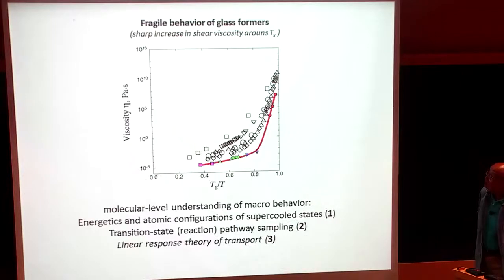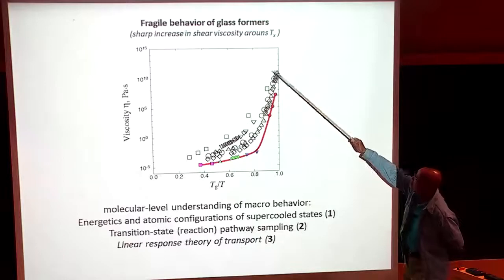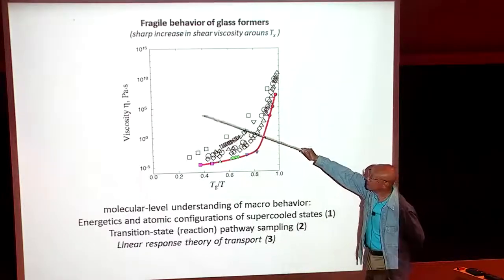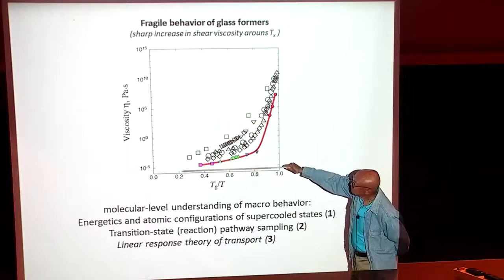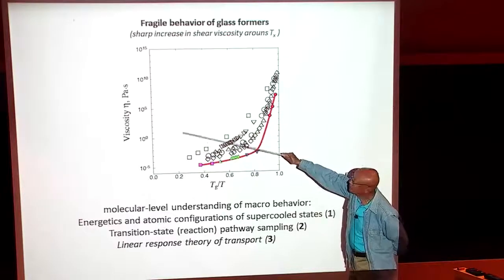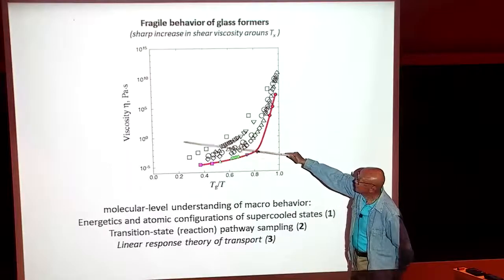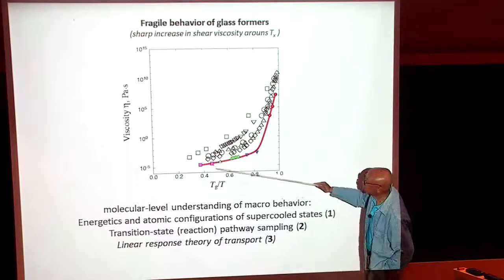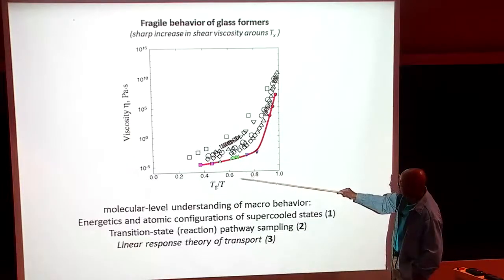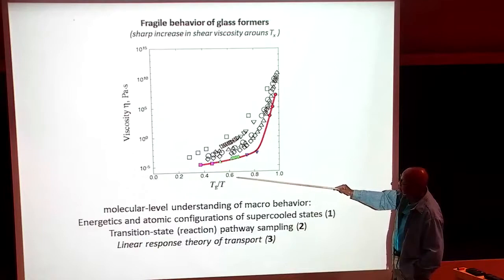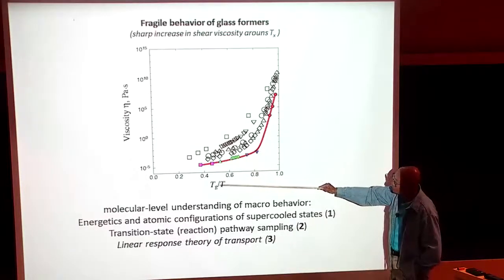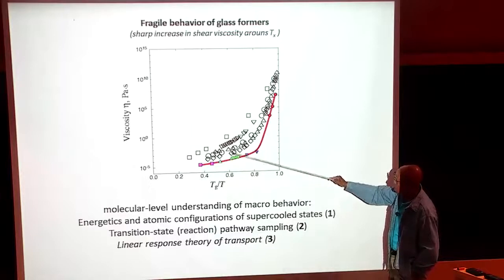It started out, I guess, the plot like this is sometimes called the Angell plot, named after Austen Angell, who did it in the 1980s. And he took a lot of data. There's a lot more data. The Angell plot has a lot more data on the viscosity of glass-forming liquids. So you're plotting viscosity here over many orders of magnitude, about 20 orders of magnitude in real units, all data now. There's no scaling on the y-axis, but on the x-axis, instead of plotting the temperature, Angell decided to plot Tg, which I'll define, over T, so 1 over the temperature.